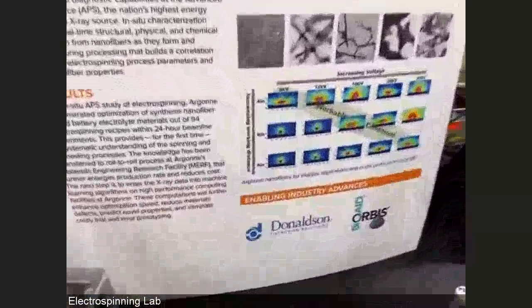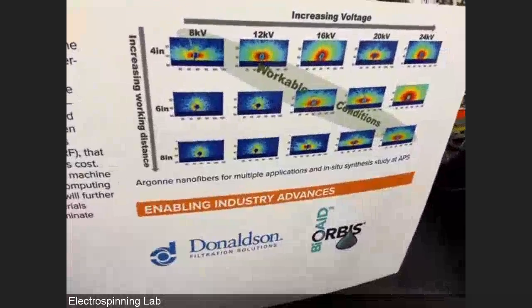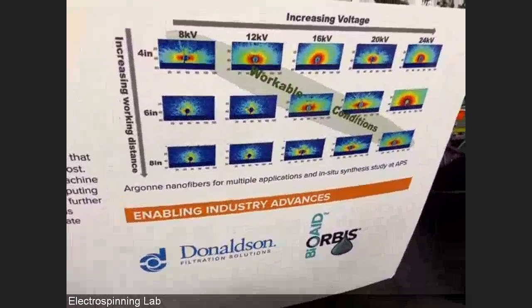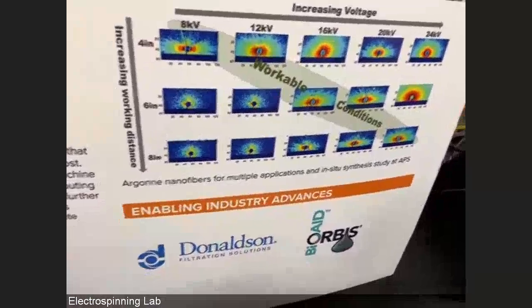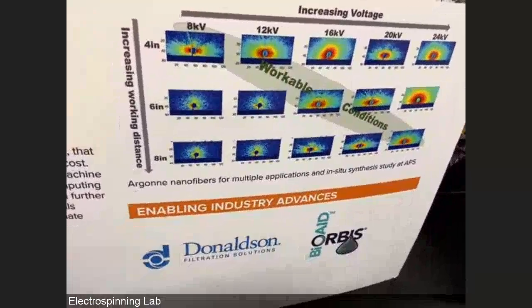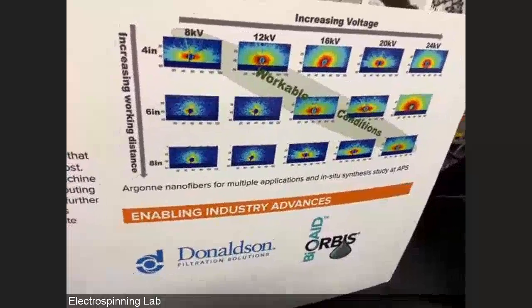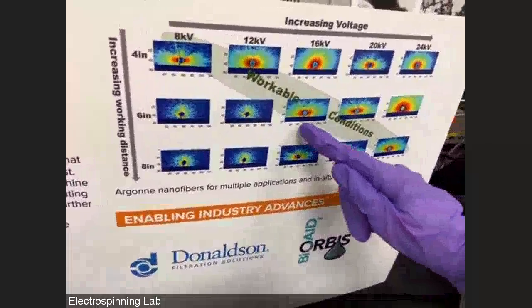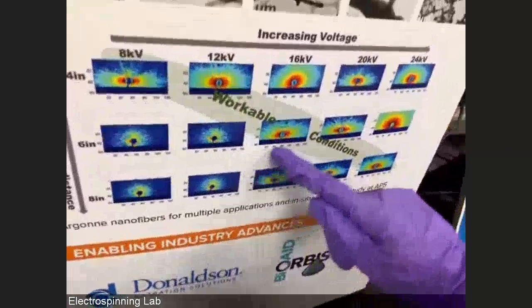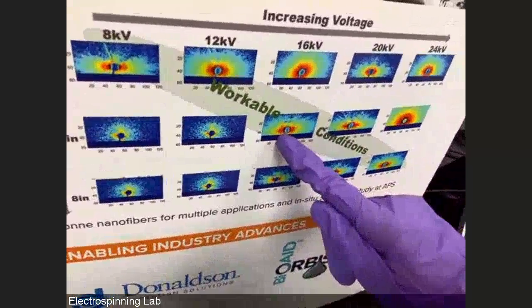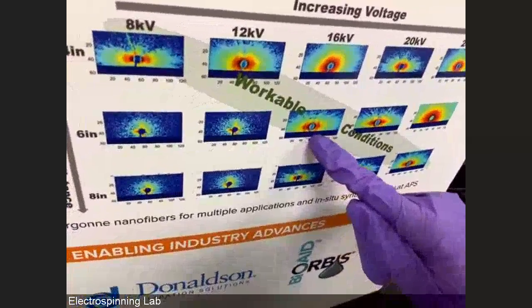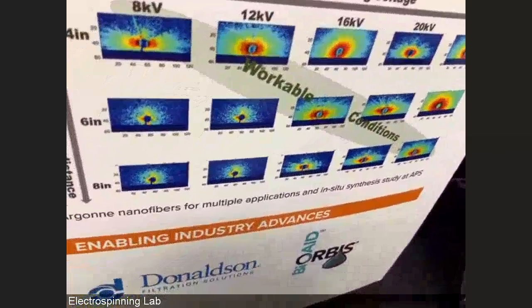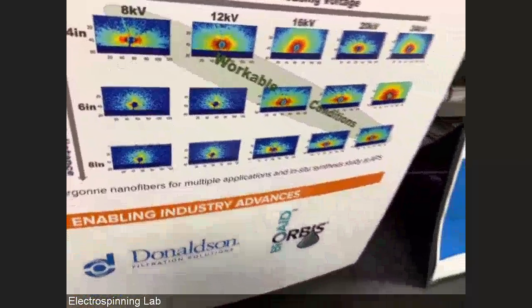So this is a typical experimental setup, the small angle X-ray scattering that we did with the setup at APS. The small angle scattering is that the X-ray beam scatters with the diameter of nanofibers. And if your nanofiber has a very uniform size distribution, you are expected to see the oscillation of intensity as a function of the wave vector. As you can see, we have dark weak color and dark color and light color. These are the scattering of your X-ray intensity when the X-ray interacts with your sample. However, if your sample has a large size distribution, you will not see the scattering effect.